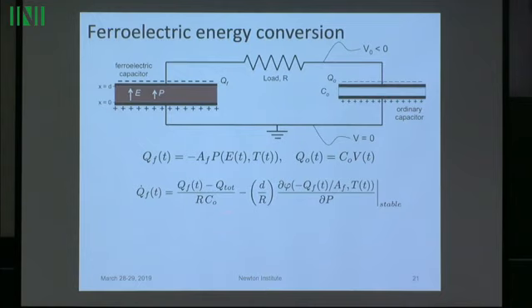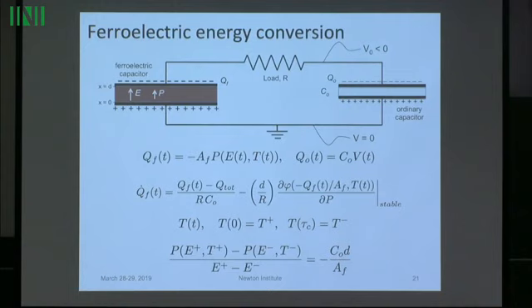So the active material is contained in this dphi dp, and we have to be on those stable branches that come from energy minimization, and this comes from the ordinary capacitor. And then the temperature versus time is something we prescribe. And we can think about good functions of temperature versus time. So we could go from a high temperature to a low temperature.